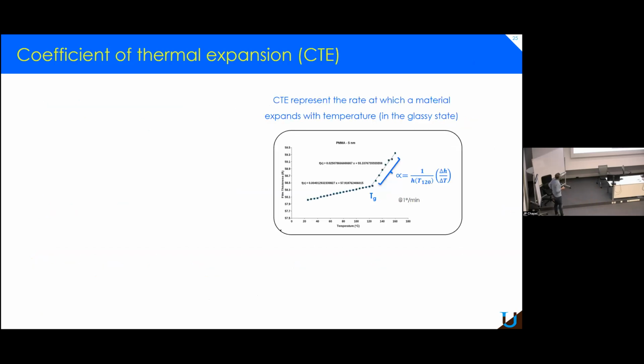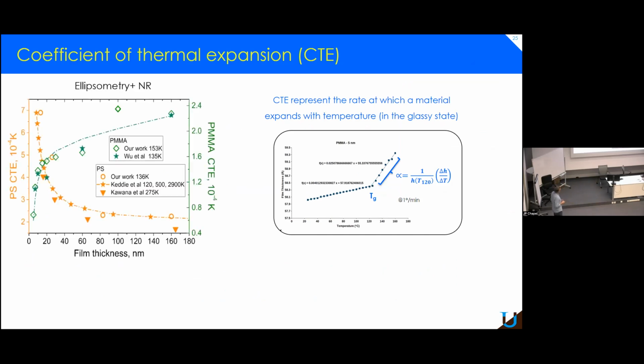So what we did is what a lot of people did in the past and even now. We measured the coefficient of thermal expansion. We spin coated the polystyrene and PMMA films, and as a function of the thickness, we made a ramp. When you increase the temperature, it's a linear variation below the glass transition, also above, and there is a kink, and the kink is the glass transition. So we are able to measure the coefficient of thermal expansion. And if you plot it as a function of the thickness, this is what we did. We also put in those graphs the data coming from all the people in the literature.